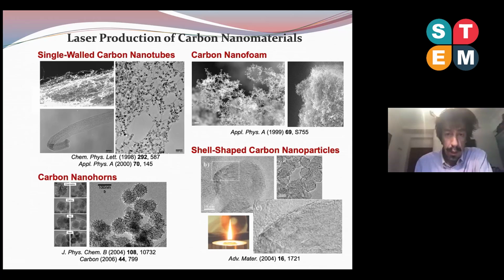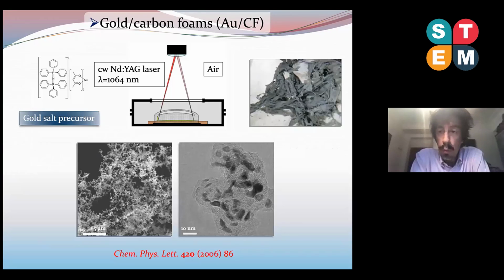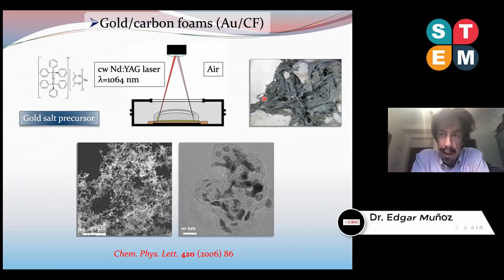And so one day in the lab, we were working for a company that was interested in making gold coatings on ceramic tiles. So what we did is we deposited a thick layer of gold salt precursor, which is an organometallic gold complex. And we irradiated it with a continuous wave neodymium YAG laser. And we observed the formation of this kind of soot, which is like a spider web soot, that resembled very much the texture of the soot we produced when we were producing carbon nanotubes.